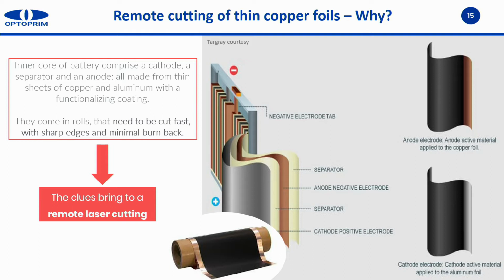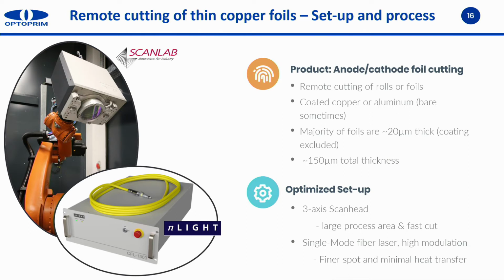All this information tells us that the approach is to use remote laser cutting. So what is remote laser cutting based on? A laser. In this application, we are going to use an infrared laser, a fiber laser with a single mode, so that we can have a very fine beam and so a higher intensity in order to properly treat copper, and also a scan head with an f-theta lens that allows us to go very fast and cut these foils over a large area. The type of material, in this specific case, was copper. Usually it is 20 micron thickness, and you have a coating on top, which brings the total thickness up to 150 microns.